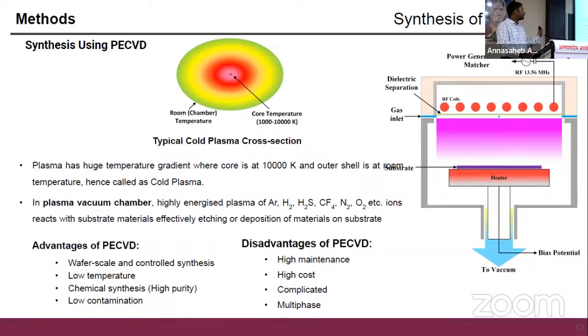We can use many substrates in order to synthesize it. And since I hope you guys may know about the plasma, basically, plasma is considered to be the fourth phase, and it has some cloud of gases with ions and anions. So typically, if you see the cross section of plasma, at the center there is very high temperature, but at the outer shell it is almost at room temperature. So it is also called a cold plasma. And since this plasma CVD machine is based on this cold plasma generation of the gas molecules, it is also considered to be a cold plasma CVD.